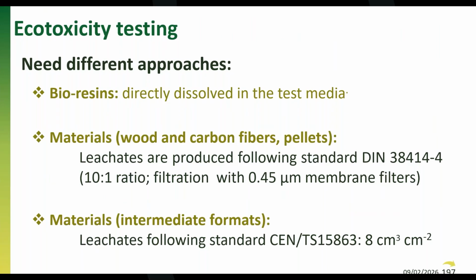But then for the materials like the wood and carbon fibers and the pellets made of the different bio-based and fossil-based polymers, we cannot dissolve them in the water that is going to be used for the ecotoxicity assay. So we needed to produce leachates, and this was done according to a standard guideline that is mentioned here, by using a 10:1 ratio, and then we needed to filtrate the eluate that was produced. And then for the intermediate formats, of course, we also cannot dissolve them into test media, so we also needed to generate leachates. But for this, the regulations suggest another standard guideline, that uses a ratio of 8 cubic centimeters of the formats per square centimeter of the aqueous media. Next slide, please.